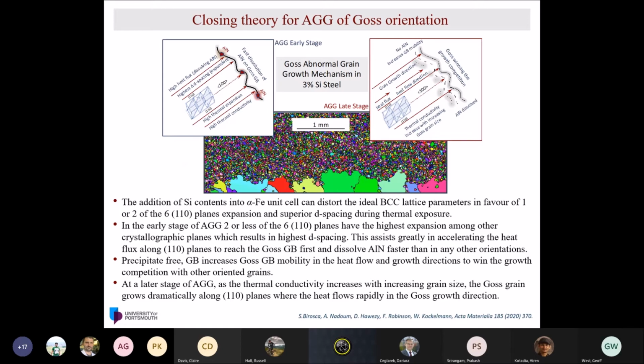So what we have to distinguish, and our solid conclusion, is that we have to distinguish between the early stage of abnormal grain growth and the late stage of abnormal grain growth. So many grains on the edge can't grow normally, but only Goss grains are predominating, and that's related to two factors.